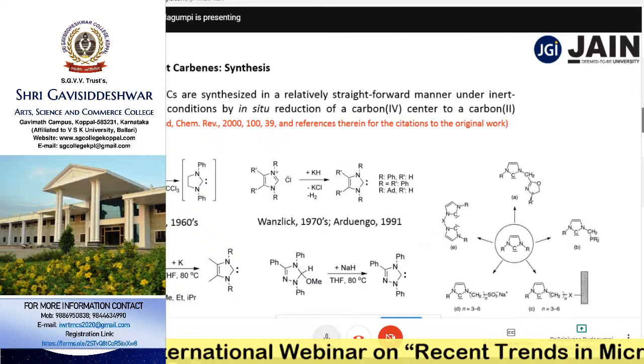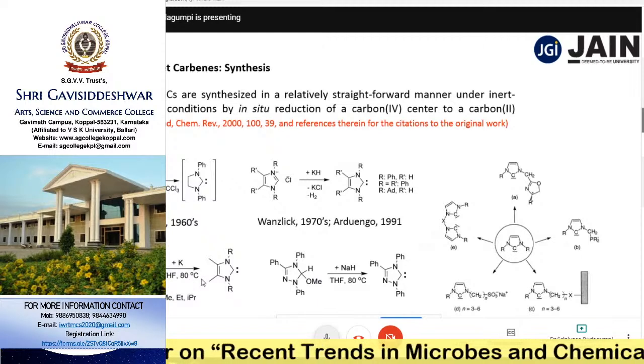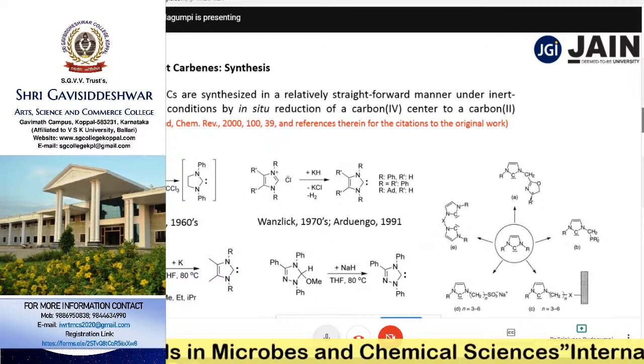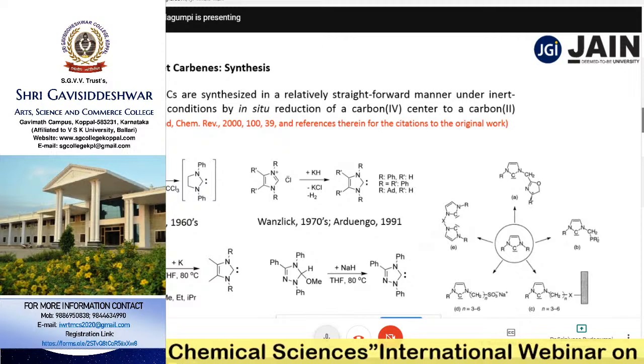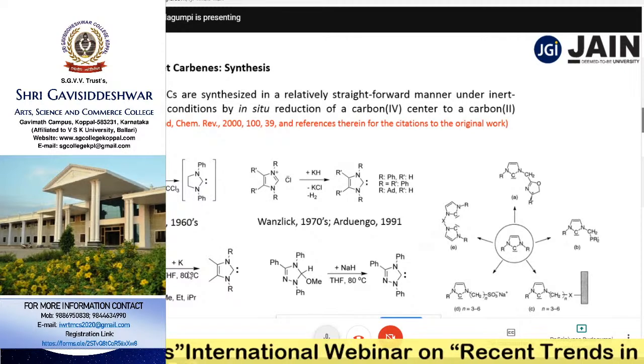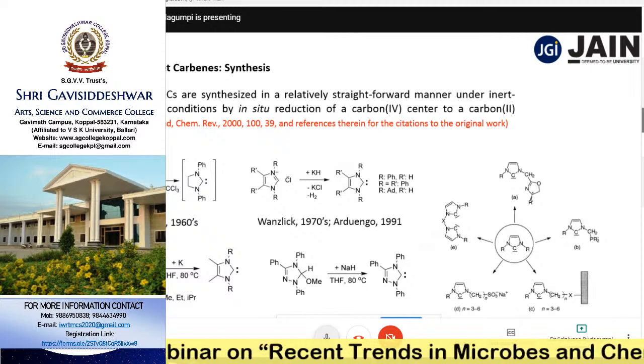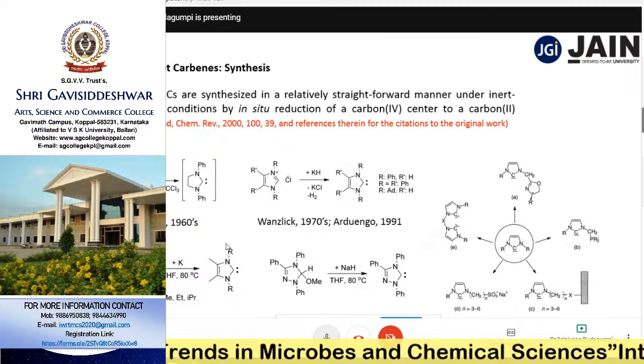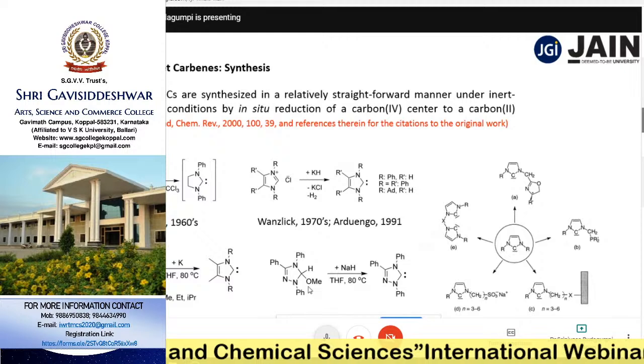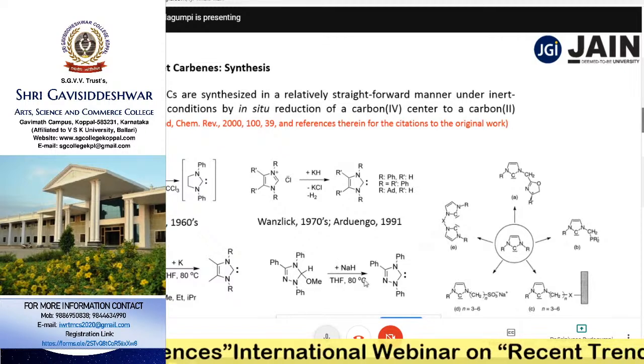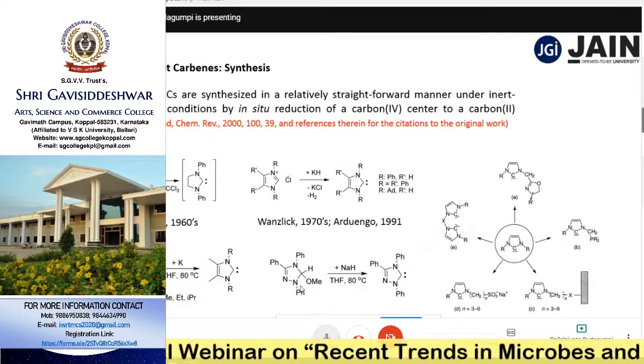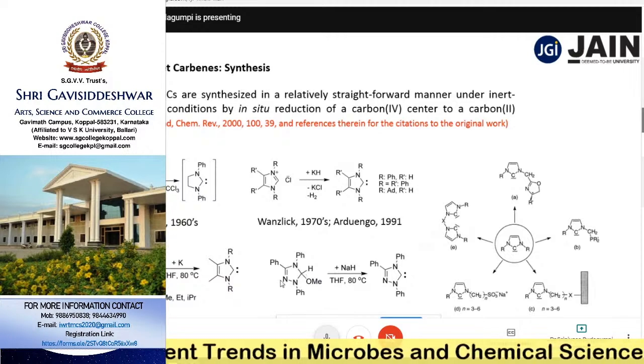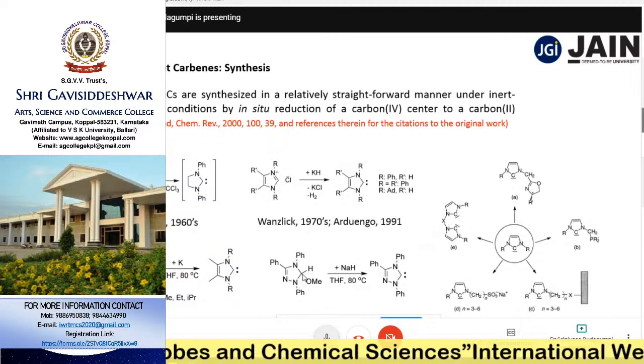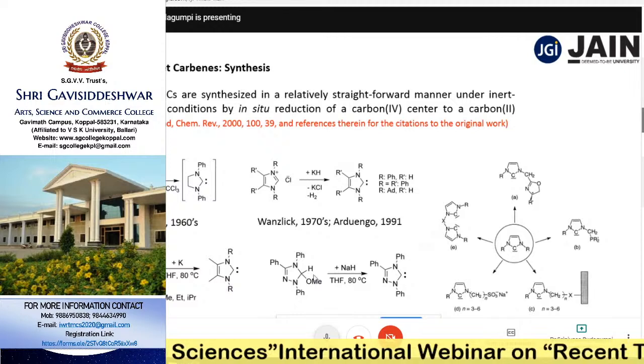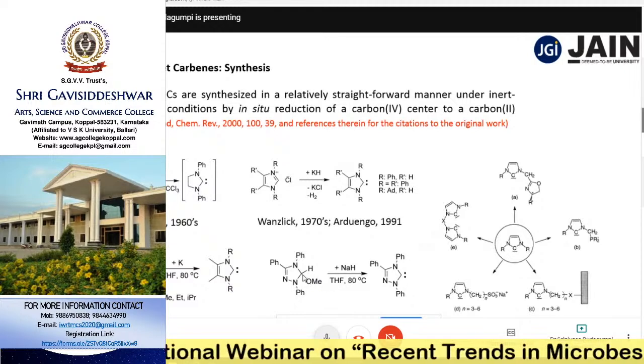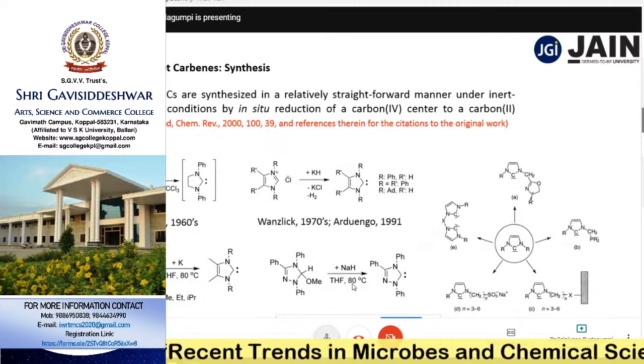While in 1993, a full-fledged carbene isolation procedure was established by Kuhn, a German scientist. An imidazole-2-thione derivative upon treatment with metallic potassium forms K2S, and that generates a carbene here, and these carbenes are quite stable. While in 1995, Enders worked on triazolium salts. This is a 1,2,4-triazolium derivative, which has a methoxy substitution at the 5th carbon atom, upon treatment with again a strong base at slightly elevated temperatures.